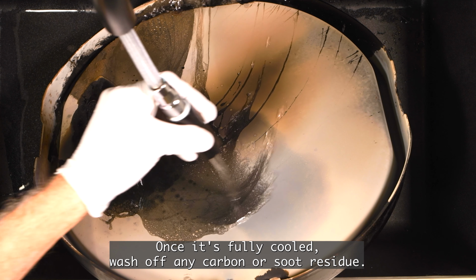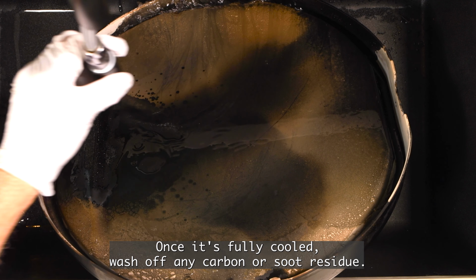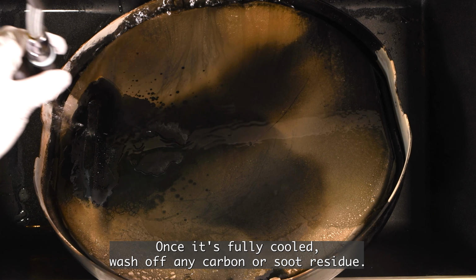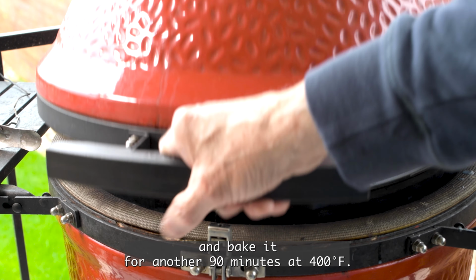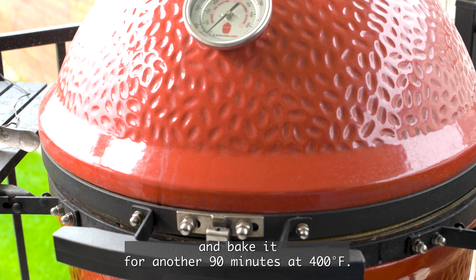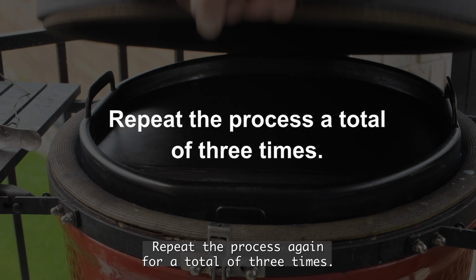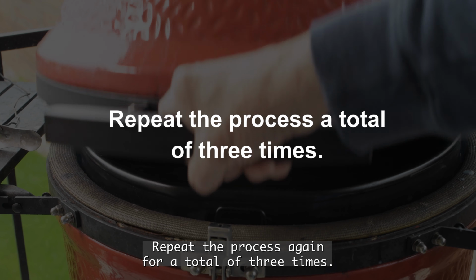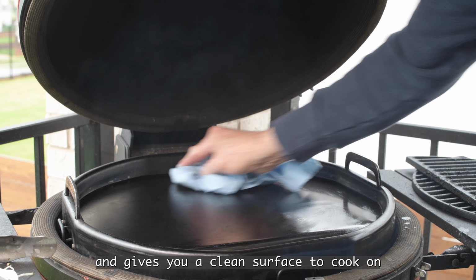Once it's fully cooled, wash off any carbon or soot residue. Dry it thoroughly on the heat source. Apply another thin coat of oil, wipe it all off, and bake it for another 90 minutes at 400 degrees Fahrenheit. Repeat the process again for a total of 3 times. After the third time, wash off any carbon or soot residue, dry it thoroughly, and apply one final thin coat of grapeseed oil before putting it away. That final coat protects the fresh seasoning during storage and gives you a clean surface to cook on next time.